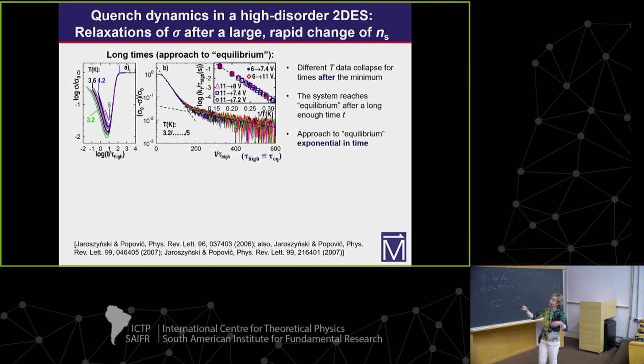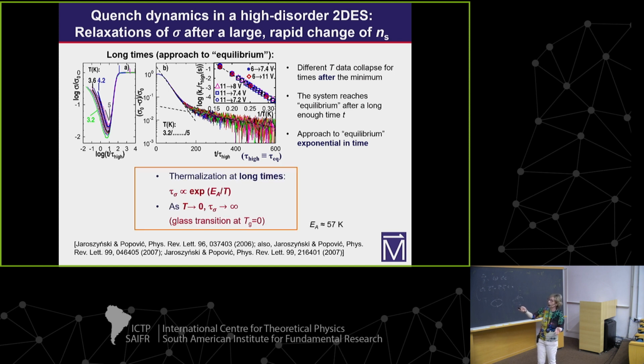We can extract characteristic times for each temperature, and we find that this thermalization time depends exponentially on temperature, such that in the zero temperature limit, it diverges.